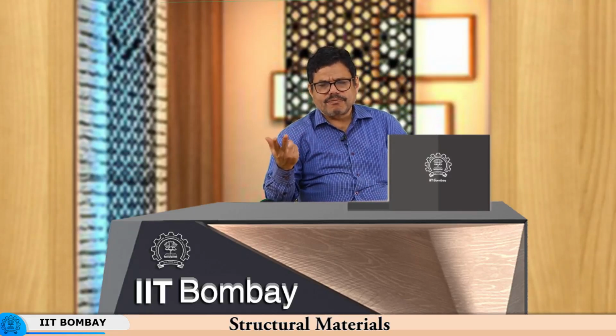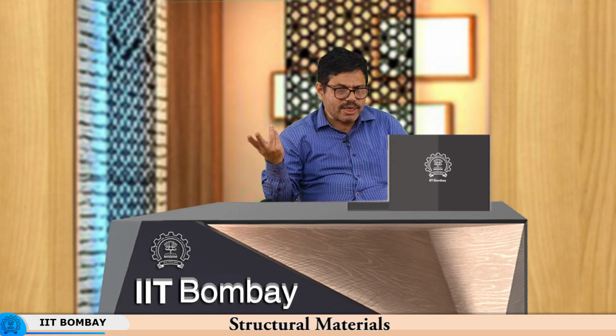But at many spots or many points, for example, you might have held the workpiece at that point using a tong or something else, and the tong did not leave any mechanical impression on it, but what the tong did was it would have changed the history of heating, altered the heating rate, altered the cooling rate, and thereby changed the microstructure. So, basically the microstructure everywhere else was probably homogeneous, whereas here the microstructure was not the same as the microstructure elsewhere, and that is one reason why we come to the topic of heat treatments.